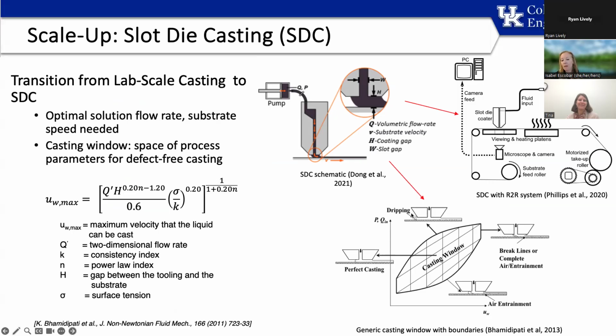And now some of the NIPS, some evaporation starts here, and we're going to have a very inconsistent membrane, a very inconsistent separation selective layer at the top of the membrane. If the flow rate and the velocity of the substrate are too fast, we're going to have just a bunch of cracks throughout the membrane.